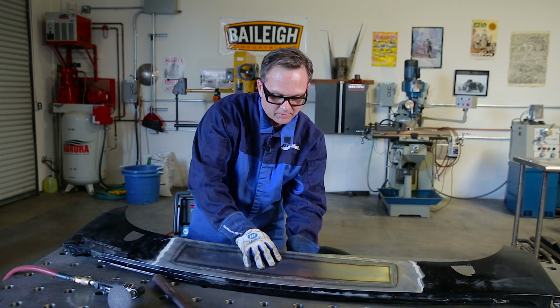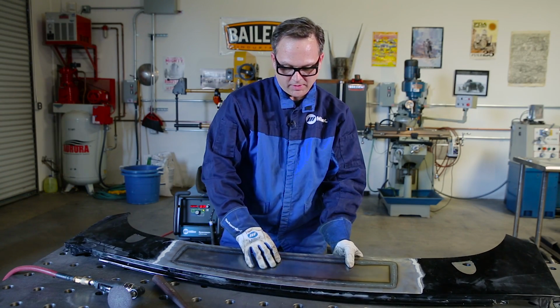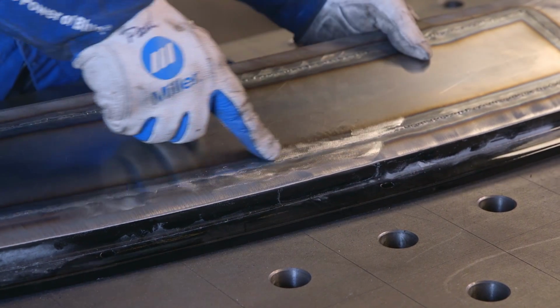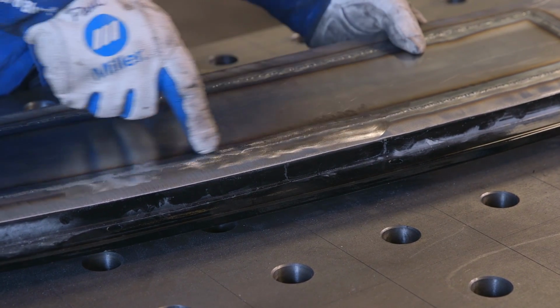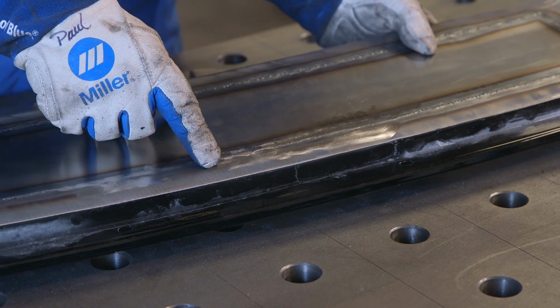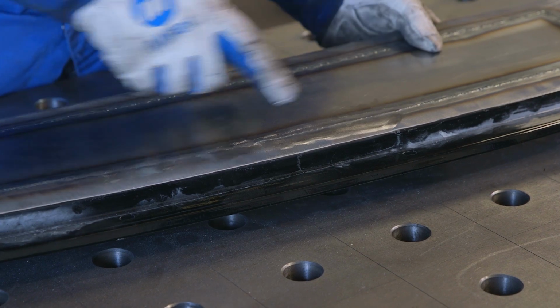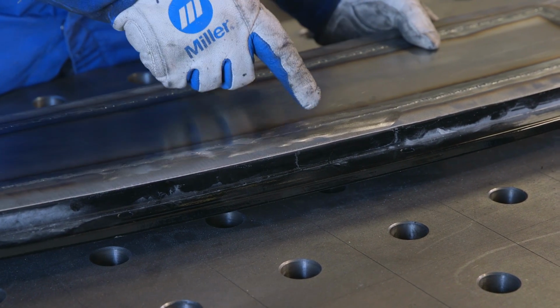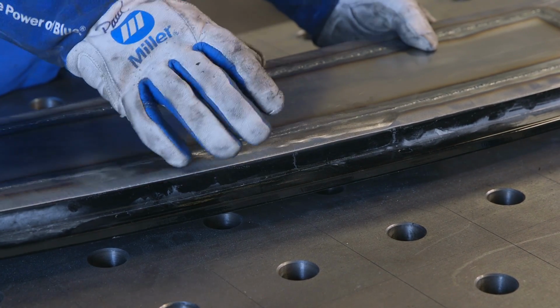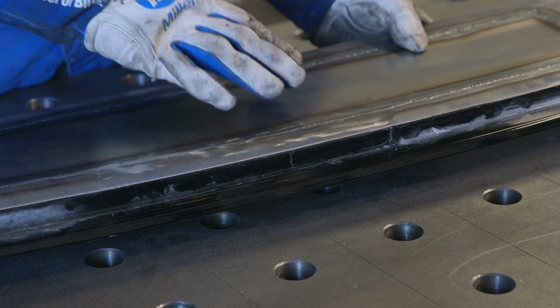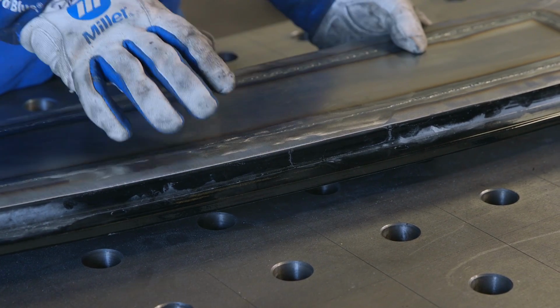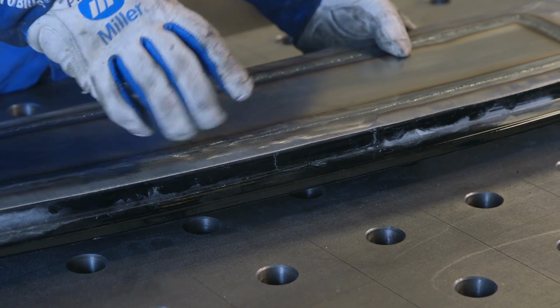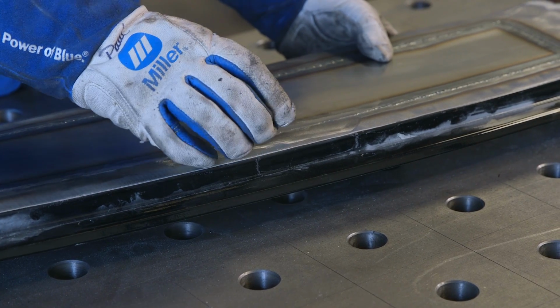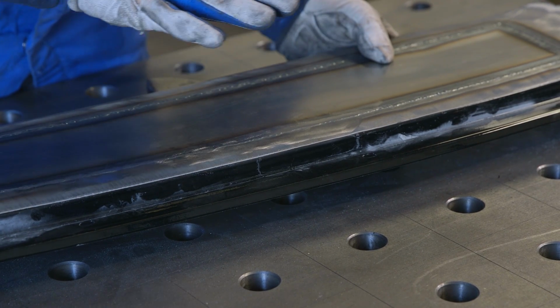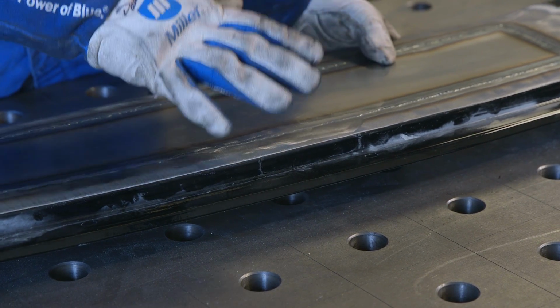And that's looking better. What that does is it actually stretches the metal at the weld. The weld metal is actually annealed, so it's softer. The filler metal we're putting in there is a little bit harder than the base metals, but it's also annealed. So I think it pretty much evens itself out. But what happened was when we welded it, it shrunk. So now we're actually stretching it back out to where it should have been originally.